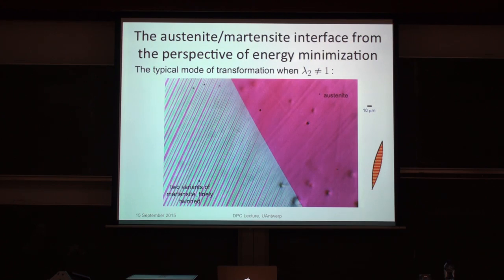Now, of course, we often see very complex microstructures. So this would be what we would see at the finest level, at least maybe not the scale bar the same, but the structure the same. And so it's quite a universal structure seen in these kinds of crystal-to-crystal phase transformations. And let me explain. There's a theory for this, and it goes back to that 1952 paper I mentioned earlier. That was quite a milestone in the understanding of phase transformations, because if you look at that interface, it looks beautifully crystallographic, right?